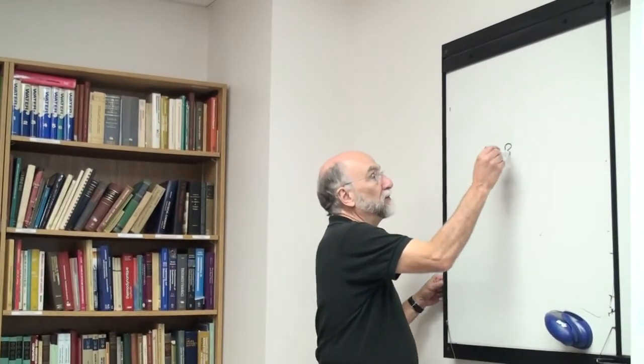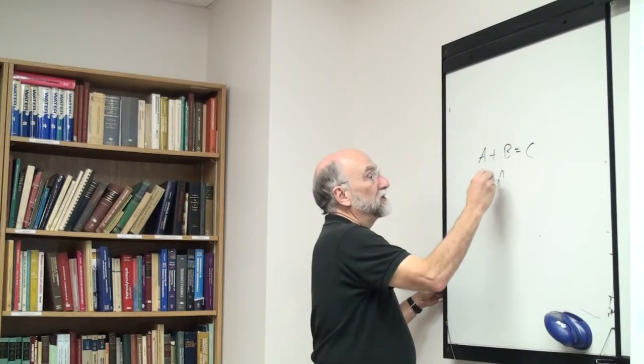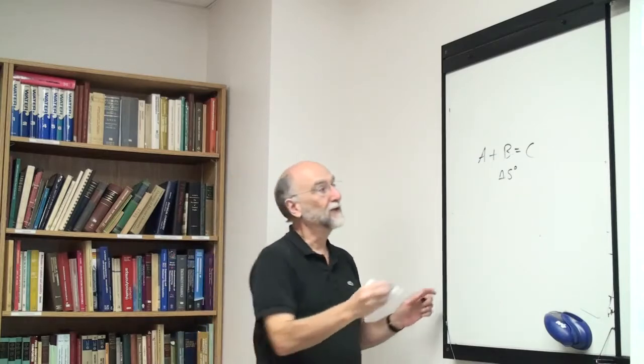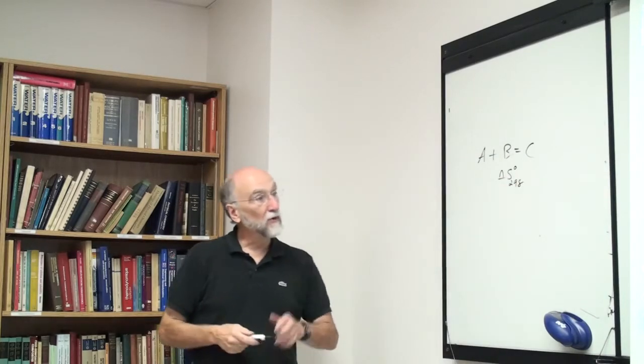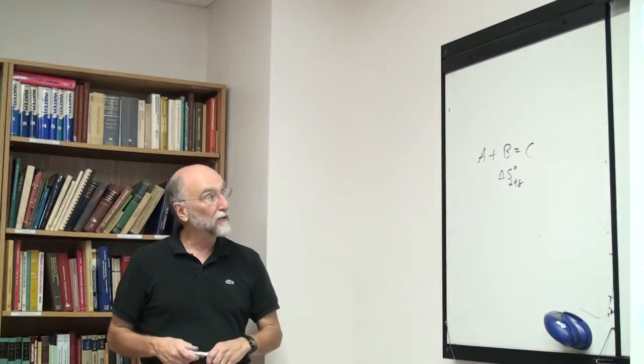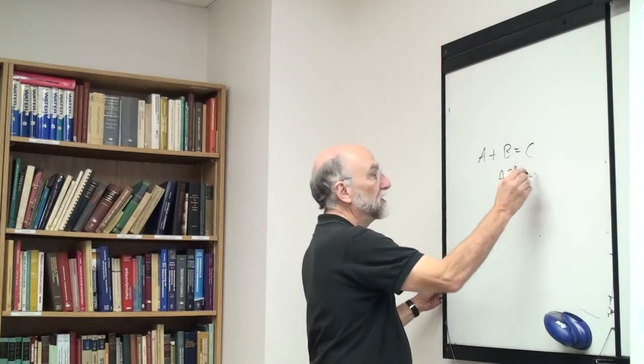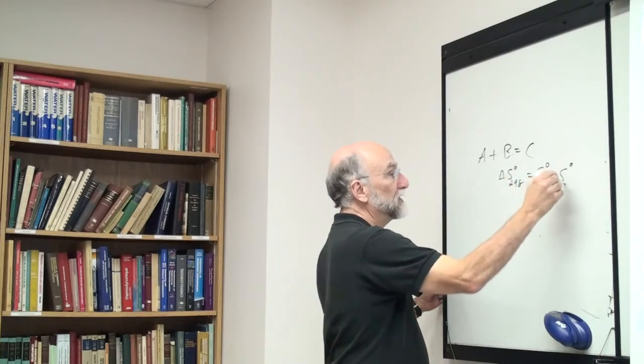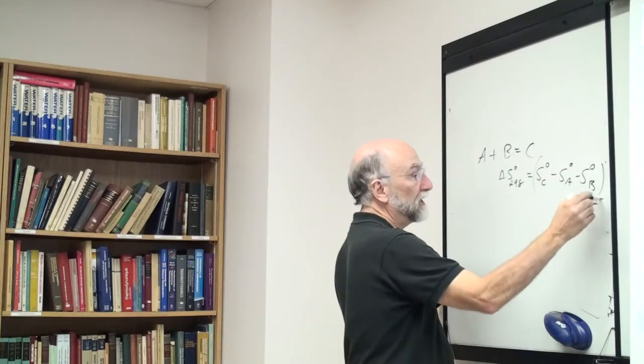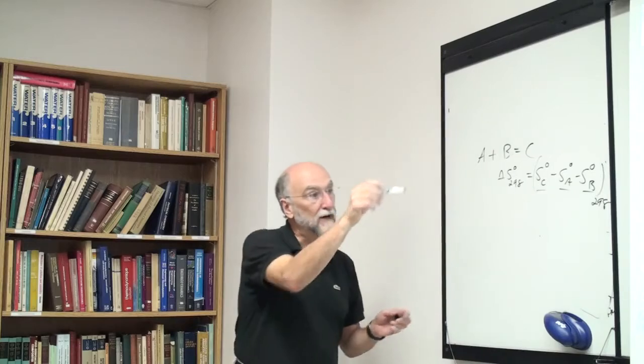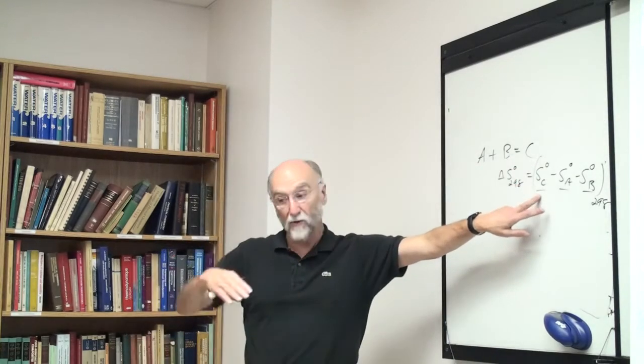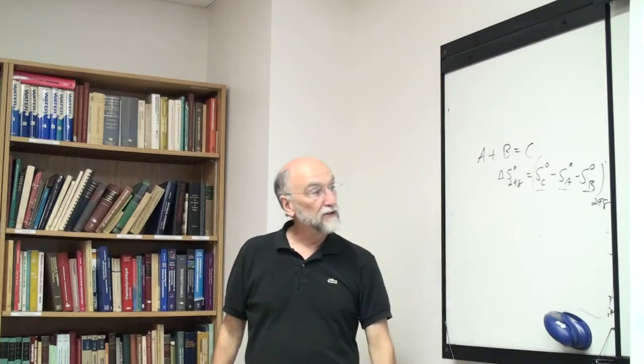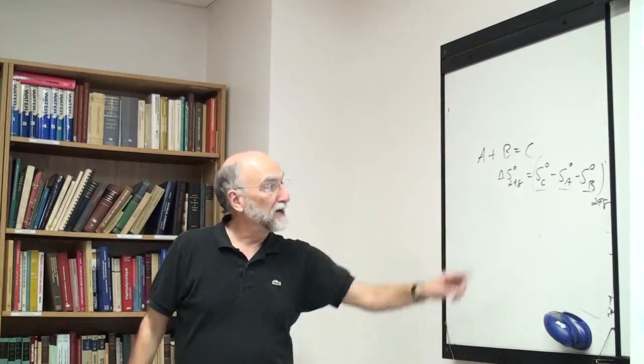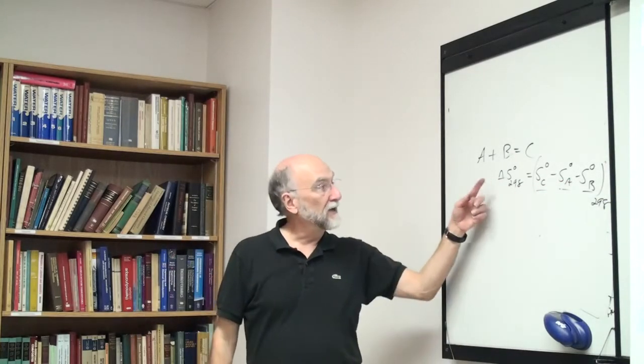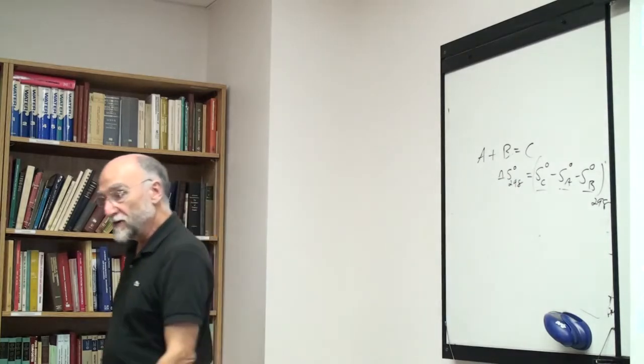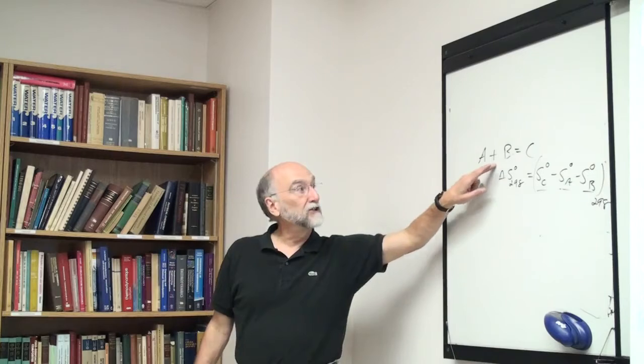So now supposing I have the reaction A plus B equals C, and I would like to know what the entropy change is for that reaction at 298. Now one way of doing it is the second law method: I set this thing up as some sort of an equilibrium and take the temperature dependence. Or, ΔS° at 298 is the entropy of C minus the entropy of A minus the entropy of B at 298. I obtain each of these individual entropies by the third law method. That is, I measure the heat capacity of C from 0 Kelvin up to 298, and the same thing for the heat capacities of A and B. Then using this equation here, I obtain the absolute entropies of the three materials, and then I can calculate ΔS at 298.